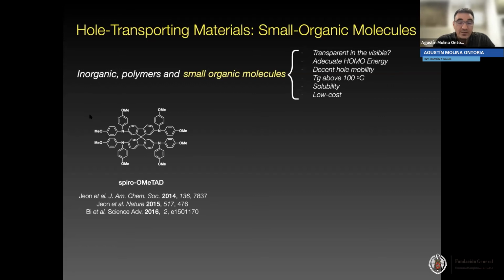So this is spiro-OMeTAD. That is the molecule that the group of Henry Snaith and Michael Grätzel used to get rid of the iodide triiodide liquid electrolyte. And this is the reference compound for everybody in the world. Everybody is using this as a reference to see how good or how bad they are making devices. This molecule is transparent in the visible, possesses an adequate HOMO energy, and is not showing a decent hole mobility in its pristine form. It shows a Tg higher than 100 degrees and excellent solubility. You can dissolve 70 milligrams of this in 1 milliliter of chlorobenzene, but it is not low cost, because 5 grams is close to 1,500 euros.